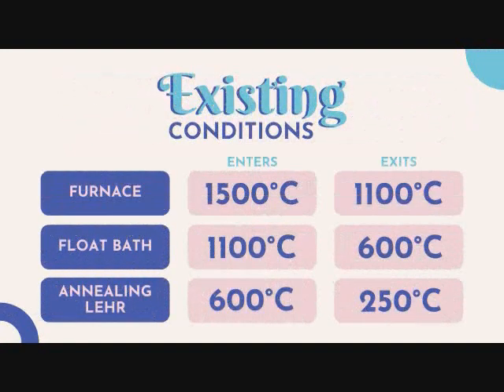Now let's look at the conditions that exist within the Pilkington process. The raw materials first enter the furnace at 1500 degrees Celsius. Then it turns into molten glass and exits the furnace at 1100 degrees Celsius. The molten glass then enters the float bath at 1100 degrees Celsius, turns into a rigid glass ribbon, and exits at 600 degrees Celsius. This rigid glass ribbon then enters the annealing layer at 600 degrees Celsius, and it is cooled until it is 250 degrees Celsius. Then it is finally ready for cutting.